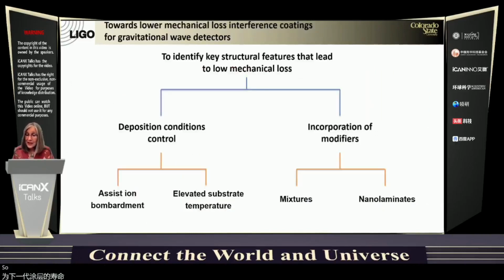So essentially what I showed you is that by crafting the materials, understanding the fundamentals of the materials, we can actually tailor their properties, in this case, this structural rearrangement at medium range, to obtain a lower mechanical loss. And we have different tools at hand. We can change the material properties by changing the deposition conditions or also by making mixtures and nanolaminates. With that, we hope to demonstrate these